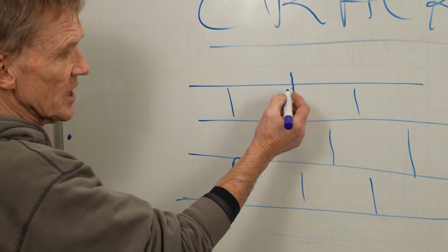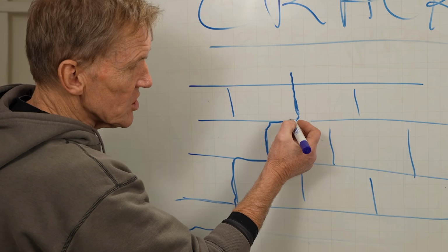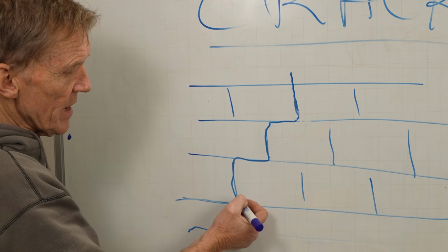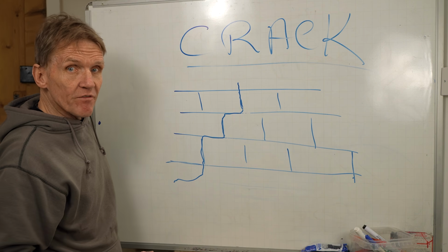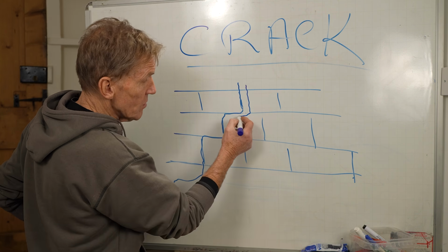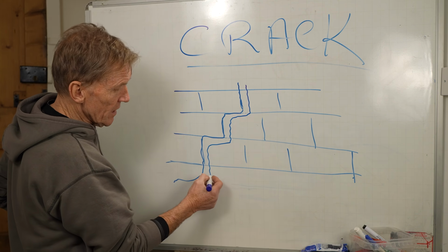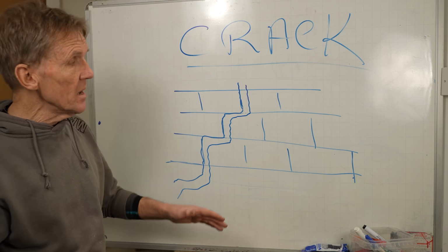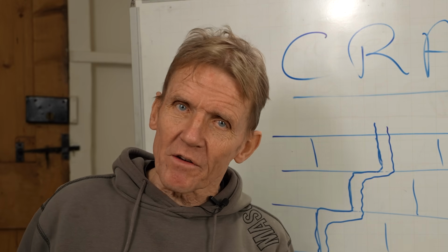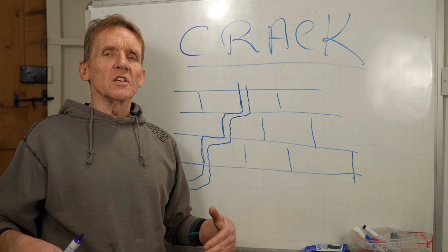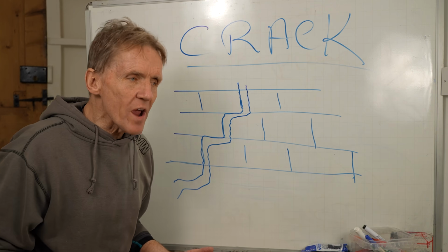If you put a straitjacket on that, if you put a nice strong resin all the way down that crack, what you find very often is that the brickwork will just crack next to it. And I've seen that time and time again, where there is a crack next to the crack, if you like. The first thing you need to do is find out why that crack is occurring.